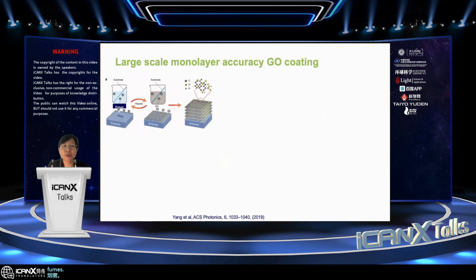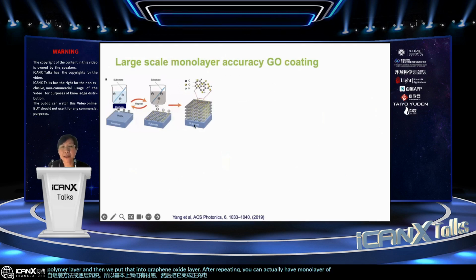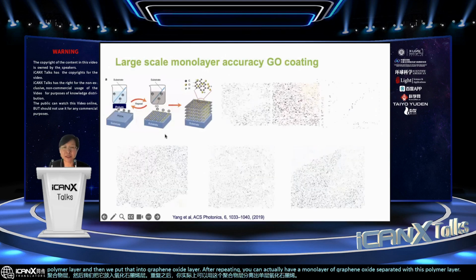So in that case, we want to control the monolayer, because in optoelectronic devices, monolayer is really important. It's also very easy to integrate with existing devices. So in this case, we developed a method called the self-assembly method, or layer by layer deposition. Basically, we have a substrate and then put that into a positively charged polymer layer, and then we put that into a graphene oxide layer. After repeating, you can actually have a monolayer of graphene oxide separated by the polymer layer. In that case, you can repeat this process to get as many layers as you want.